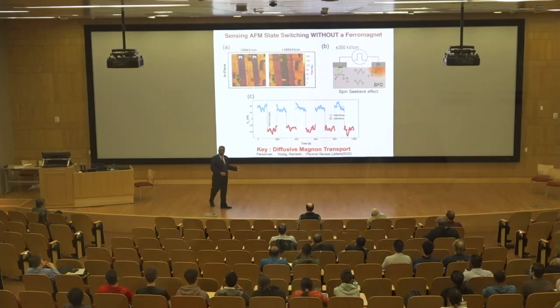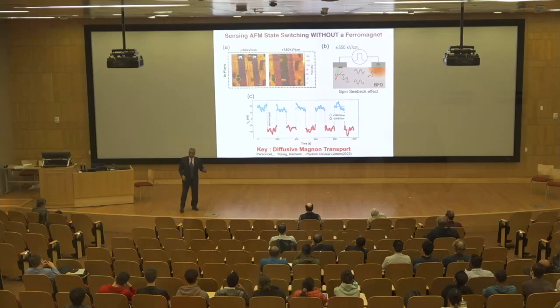What Eric found and Lucas found was that they could indeed get an output voltage of about 50 nanovolts. Not a huge value, but they could measure it. But interesting was that the polarity of that voltage or the current was changing as I switched my ferroelectric, which is white here and it's black here. You could see it goes from the red to the blue.